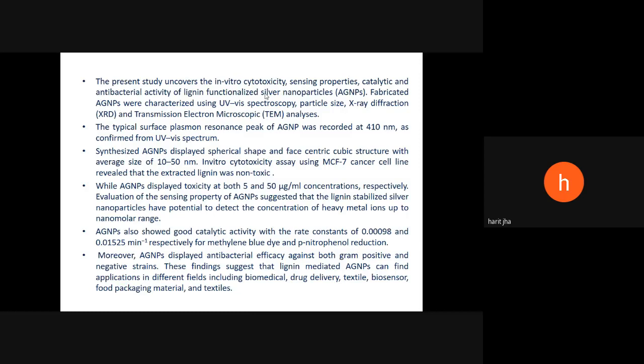this synthesized silver nanoparticle displays spherical shape and face-centered cubic structure with average size of 10 to 50 nanometer. In vitro cytotoxicity assay using MCF7 cancer cell line revealed that the extracted lignin was non-toxic, while AgNPs displayed toxicity at both 5 and 50 microgram concentration respectively. Evaluation of the sensing property suggested that lignin stabilized silver nanoparticles have potential to detect the concentration of heavy metal up to nanomolar range.